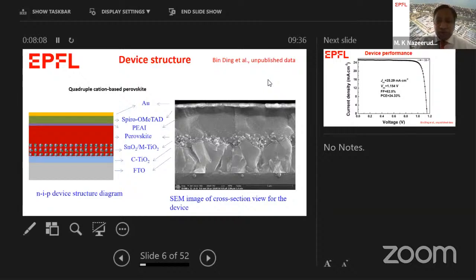So this is our typical configuration of a perovskite solar cell in a NIP type. And if you look at the thickness of the perovskite absorber material, it is close to 600 nanometers. Now, on the left side is a cartoon just to give you a clear picture of our NIP configuration. Using this type of NIP configuration, the next slide shows you the power conversion efficiency reached in our lab, which is 24.3%.